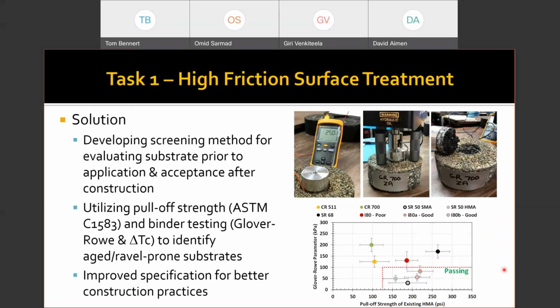The second thing we did was develop a high friction chip seal product, something that we're evaluating. There's a section of it on, oh my gosh, Route 68 right now. And we're looking at a couple more applications around the state where, as opposed to an epoxy resin, we're using a heavily polymer modified asphalt binder to do the gluing, something that's more compatible with the asphalt pavement. So we're looking at these other alternatives, again, looking at existing specs and how we can continue to improve them. In this case, you can see that although the intention of this specification was good, the conditions in New Jersey may not lend themselves to it being applied universally across all pavements without some sort of pre-screening being done.